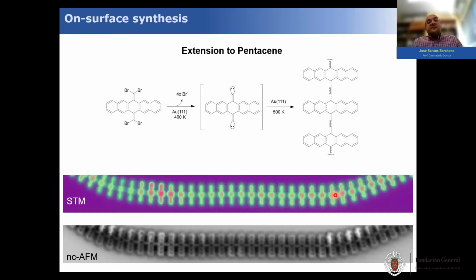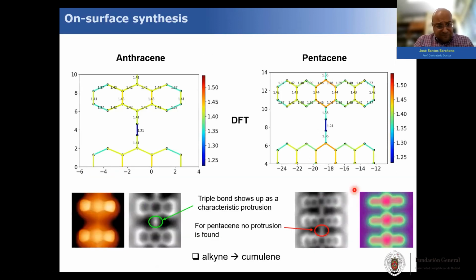We extended this protocol to a longer acene, pentacene, a molecule of great importance and relevance in the organic electronics field. And we were fascinated and satisfied to observe that what we obtained again were very nice long polymers, as you can see here from the non-contact AFM and STM images. But was the structure the same? If you observe these two images from the anthracene, you can see that in between the anthracene units we have a bright spot, whereas in the pentacene one we don't have this bright spot. This bright spot is the characteristic feature of triple bonds.